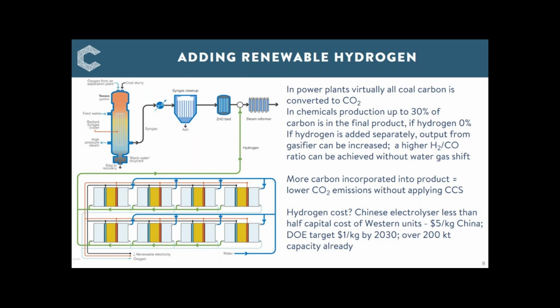But if we can add hydrogen to the mixture, then you can increase the hydrogen CO ratio without doing as much water gas shift chemistry. And that way, more of the original CO can be incorporated into the product. In theory, all of it could be, except for the inherent CO2 in the syngas in the first place. So it's possible by this route to turn almost all the coal carbon into the product, which is where the industry falls short compared to, say, ethane to ethylene, where apart from the combustion side of the steam cracker, most of the carbon ends up in useful products. So this is potentially game changing.